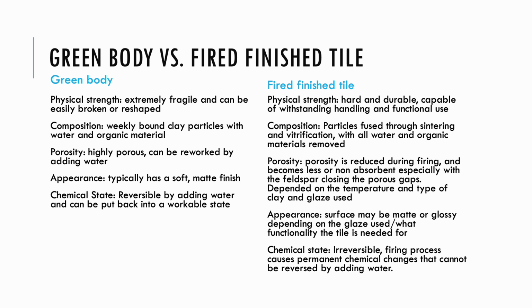Meanwhile, a fired finished tile: the physical strength is hard and durable and capable of withstanding handling and functional use. Composition: the particles are fused together through sintering and vitrification with all water and organic materials removed. Porosity: the porosity is reduced during firing and becomes less or non-absorbent, especially with the feldspar closing the porous gaps, depending on the temperature and type of clay and glaze used. Appearance: the surface may be matte or glossy depending on the glaze used and the functionality the tile needs. And the chemical state at this point is irreversible. The firing process causes permanent chemical changes that cannot be reversed by adding water, unlike the green body, which is still workable.